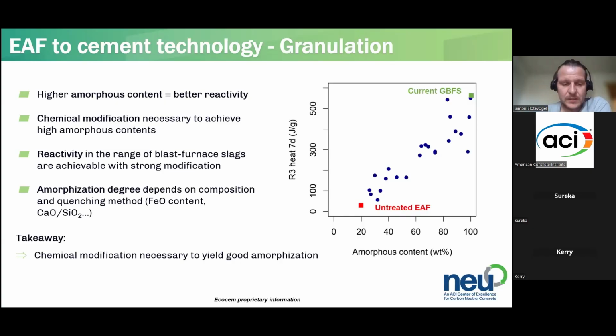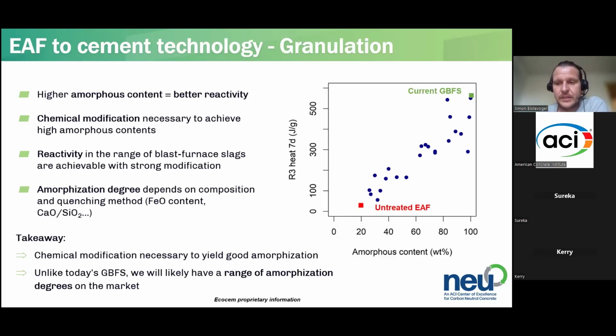So the takeaway here is maybe there's some chemical modification necessary to yield good amorphization, and this will depend very much on the effort you're willing to put. High modification will very likely yield good reactivity and good amorphous content, but there will certainly be places where you don't want, for financial or industrial reasons, to achieve full amorphization. So there will likely be a range of different amorphization degrees in the market of EAFs. But you all know the threshold values. If we reach 300 joule per gram at the amorphization of about 60%, that is already an interesting material.